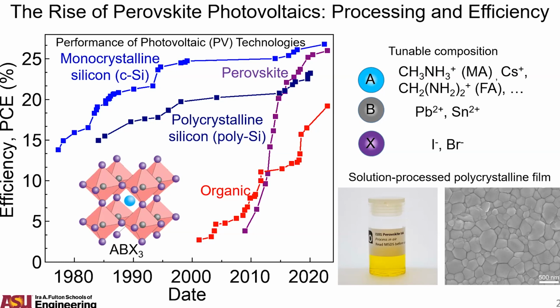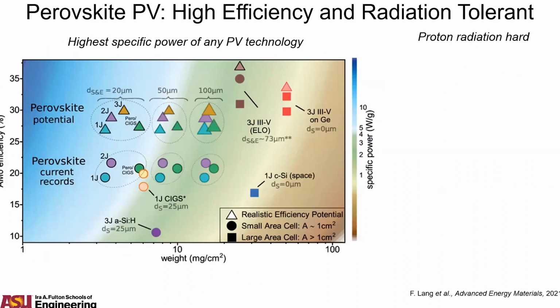One benefit of these perovskites, since they're thin films and they're very tunable in terms of their processing, is that this chart here is showing the fact that they have the potential, when integrated into tandems or multi-junctions, to reach above 30% AM0 efficiencies and to have the highest specific power of any PV technology compared to the conventional III-V gallium arsenide based multi-junction cells. The efficiencies are likely not going to be quite as high, but they can be fairly comparable. And again, the benefit is having an order of magnitude improvement in the power to weight.